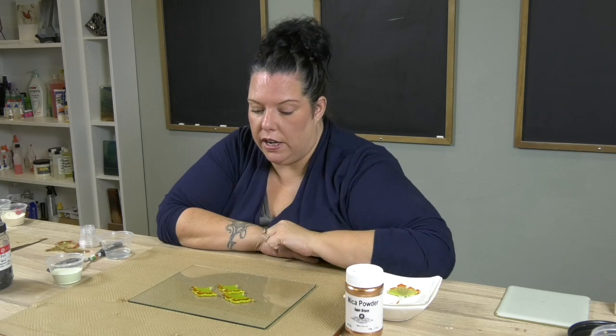Okay, whoopity-doo, big deal. But as I gave you that lecture and praised myself at the beginning of this, I was able to put mica over it with a fan brush and then fire that, and we didn't lose the powder. So I went 10 degrees longer than the schedule that I'm giving you, and the powder collapsed and did not retain the texture, because powder melts at a much lower temperature than the sheet glass does. It doesn't take much to melt the powder. It's just ground up glass, okay?